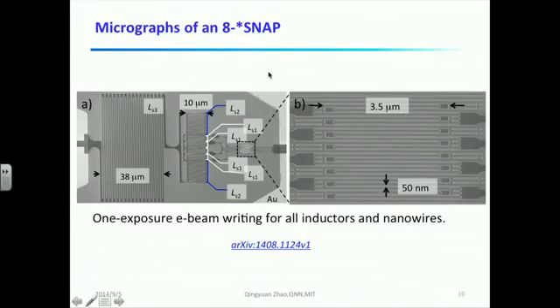And this slide shows the micrographs of an 8-SNAP. Both the inductors and the active area detectors are made of thin film. So we can use only one e-beam lithography to write the whole device. The active area consists of eight 50 nanometer nanowires. Because there are eight nanowires in parallel, the output signal is expected eight times higher. So next,